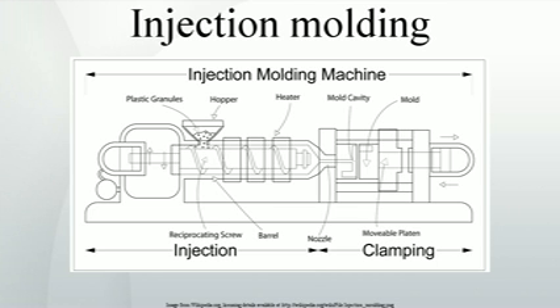When filling a new or unfamiliar mold for the first time, where shot size for that mold is unknown, a technician tool setter may perform a trial run before a full production run. He starts with a small shot weight and fills gradually until the mold is 95 to 99% full. Once this is achieved, a small amount of holding pressure will be applied and holding time increased until gate freeze-off, solidification time, has occurred. Gate freeze-off time can be determined by increasing the hold time, and then weighing the part. When the weight of the part does not change, we then know that the gate has frozen and no more material is injected into the part.